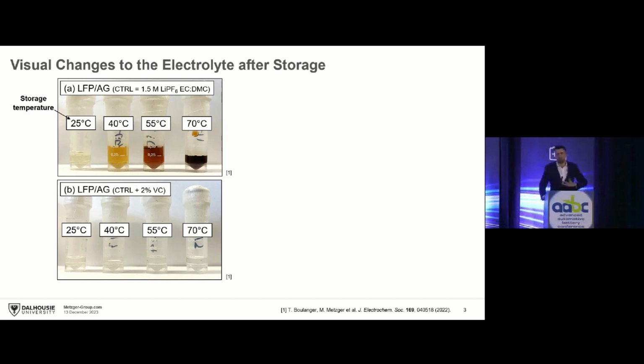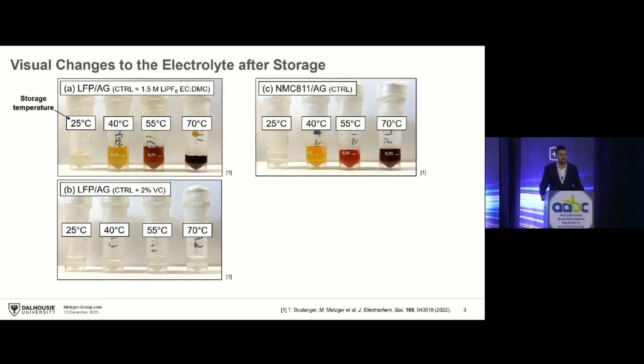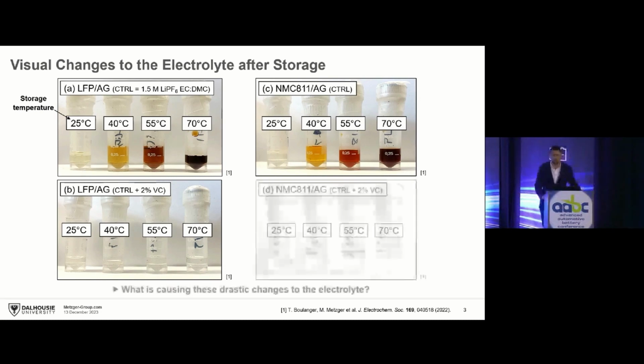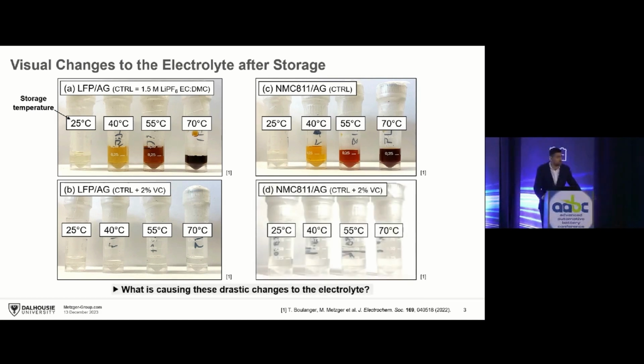So our first hypothesis as to why these LFP batteries show this rapid self-discharge and the discoloration of the electrolyte was maybe there's iron dissolving from the positive electrode. So we did the same test with NMC 811 cells that have the exact same negative electrode. It's the same type of artificial graphite. And you see the same color change, right? And again, if we use 2% vinylene carbonate, there is no color change in these battery cells. So what is causing this drastic change to the electrolyte, and is it related to the self-discharge that we measure in these battery cells?